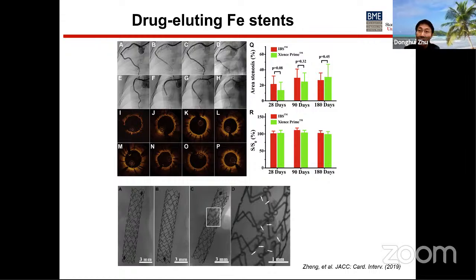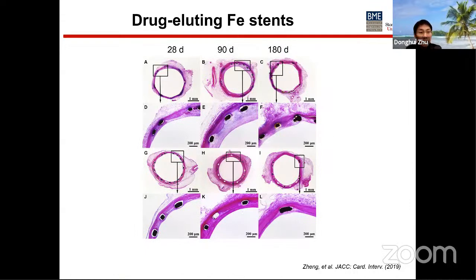But the beauty of these iron stents is that they will eventually disappear, unlike the control. This is the biggest advantage. The histological analysis shows comparable operability and midterm efficacy and safety compared to the cobalt chromium control. The IBS also showed no scaffold-associated thrombosis, no severe neointimal hyperplasia, and good mechanical support after 180 days.